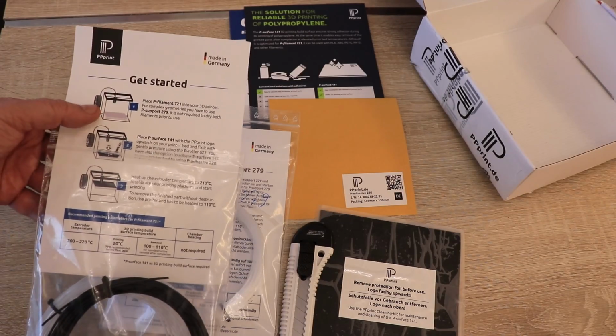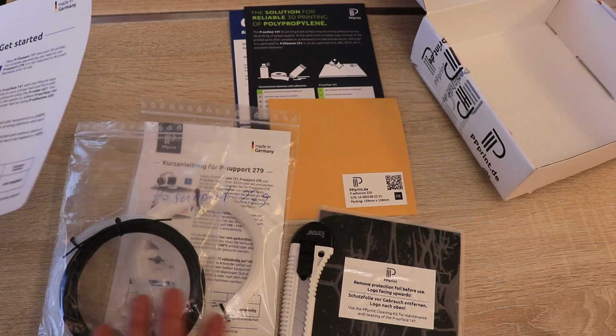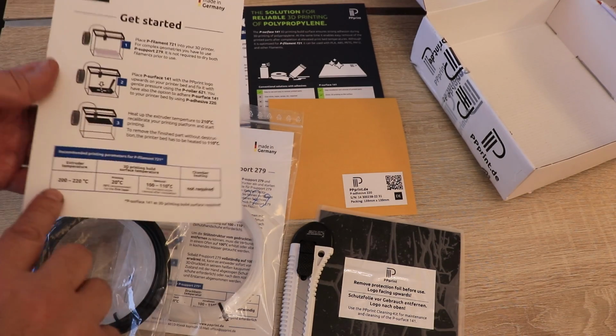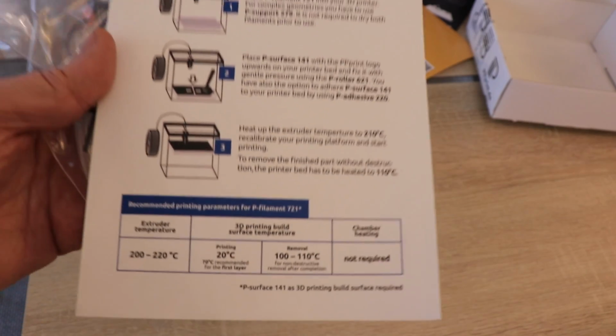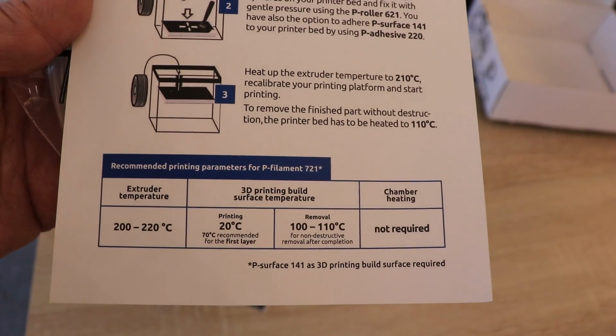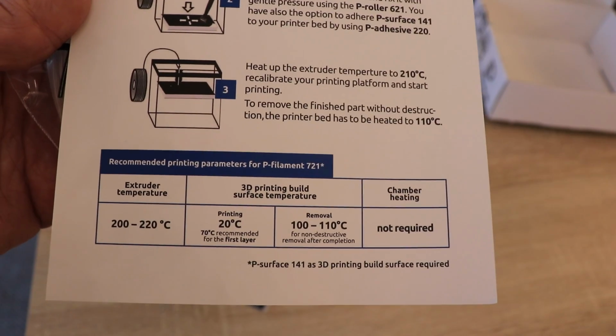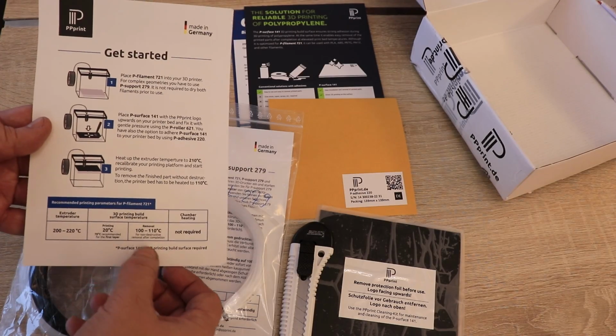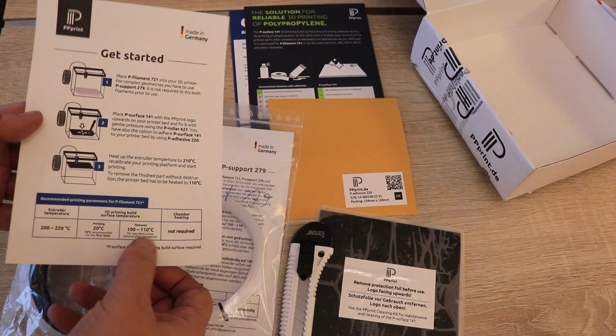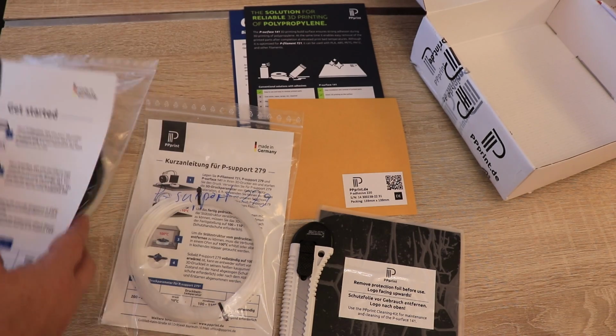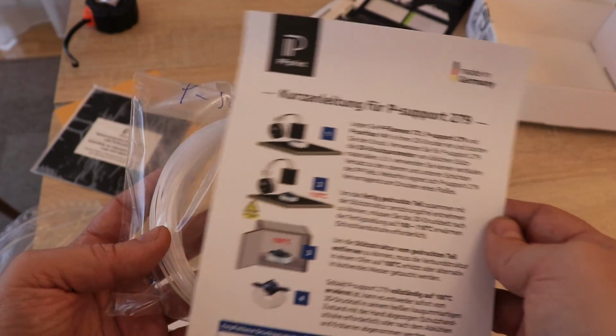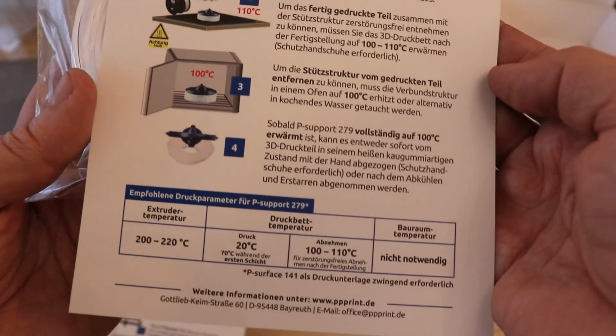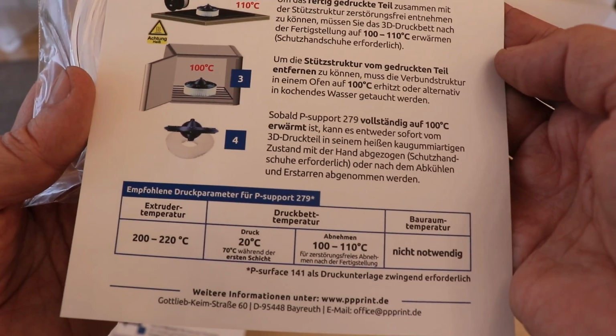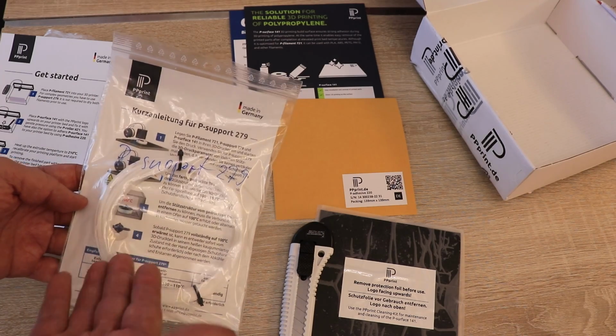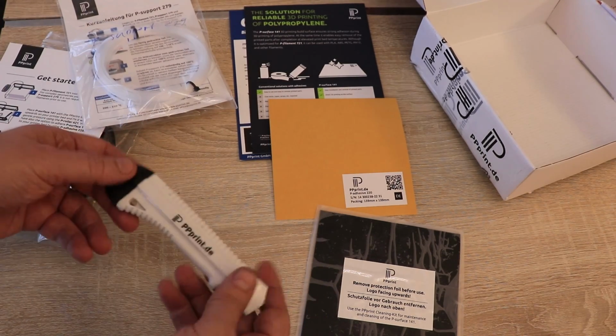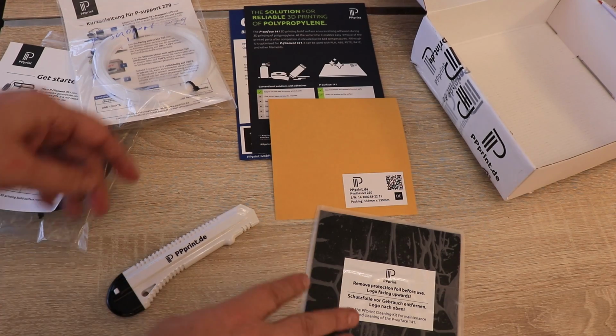So I have this PP filament 721, maybe 10 meters or something like that. Instructions: printing temperature between 200 and 220 degrees Celsius, bed 70 degrees Celsius, but for removal I have to heat up to 100, 110 degrees Celsius for non-destructive removal of the printed object. And also I have this support 279, but I don't have an IDEX printer, so I cannot test this. Also I have this cutter here, and this is that sheet.